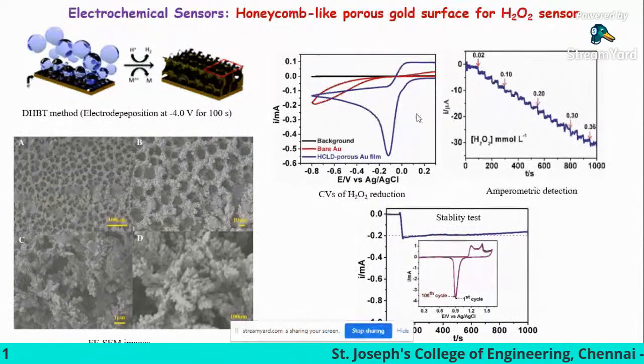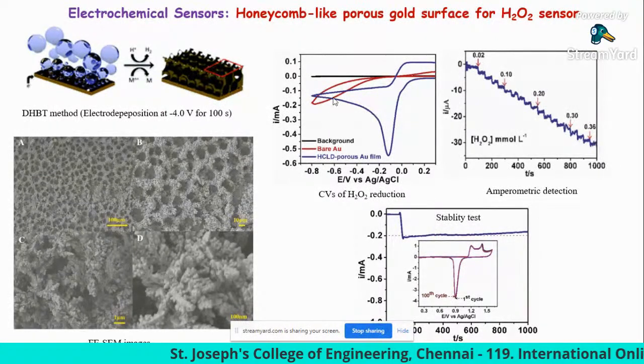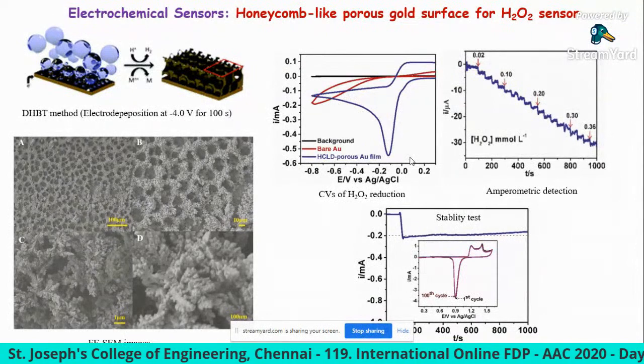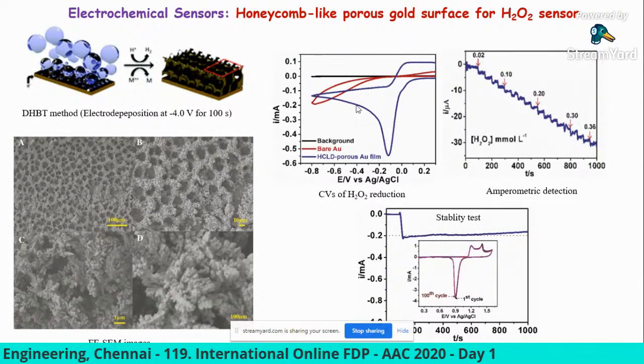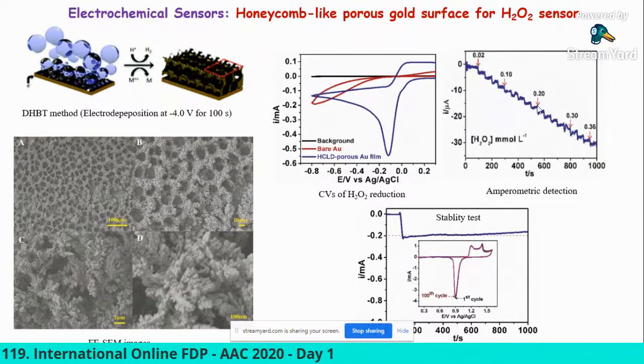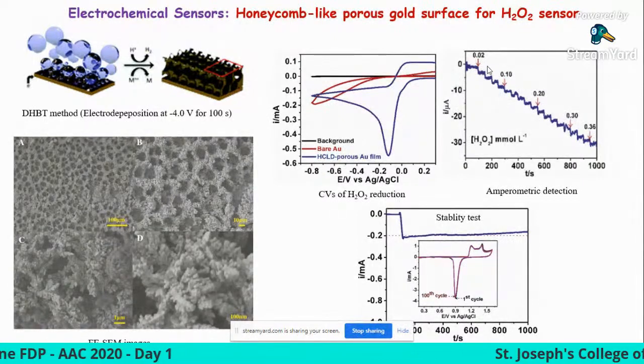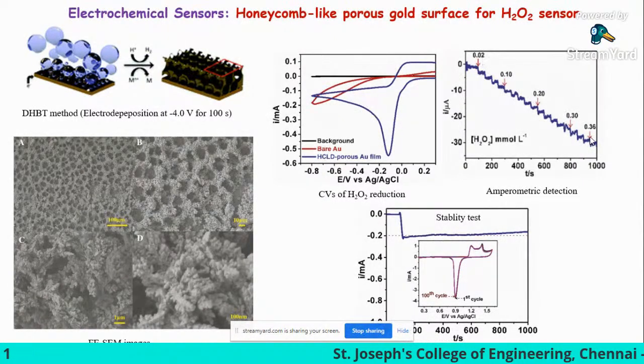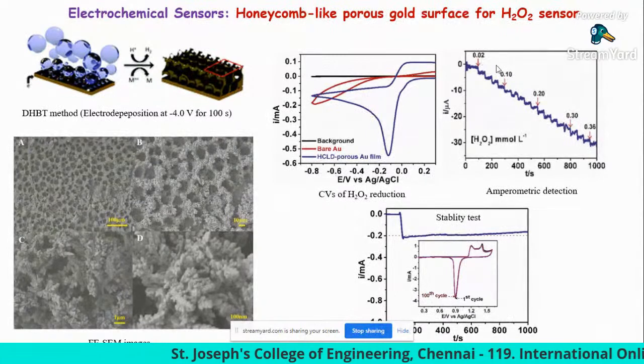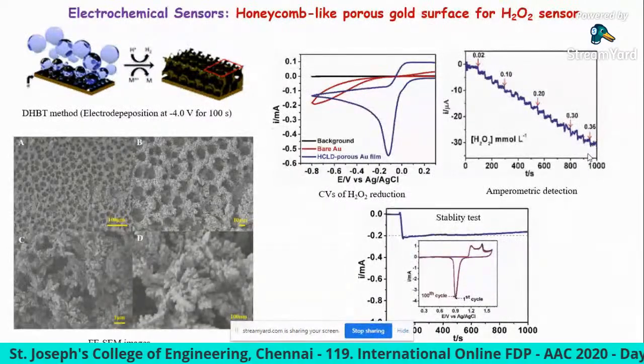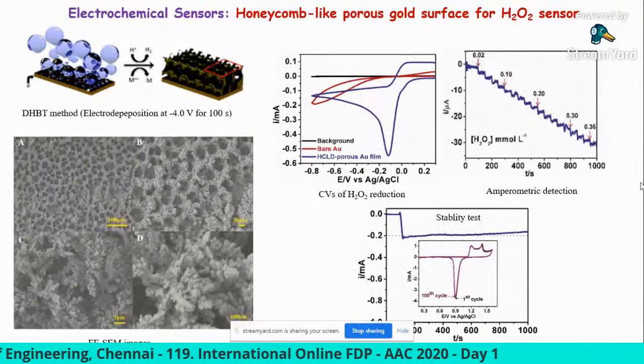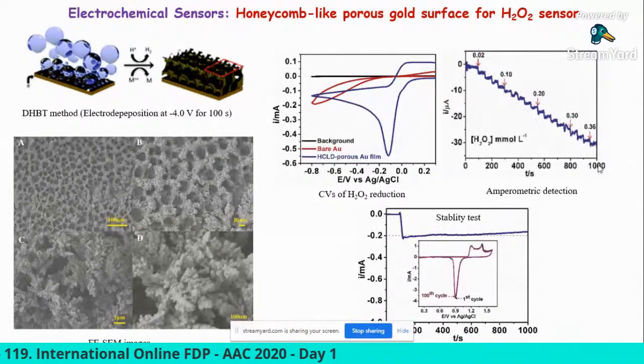Then we also evaluated this for a hydrogen peroxide sensor, where we also get excellent electrocatalytic activity for hydrogen peroxide detection. This is the corresponding amperometric response from 20 micromolar to 0.36 millimolar concentration range, and it shows a linear increment in current signal.